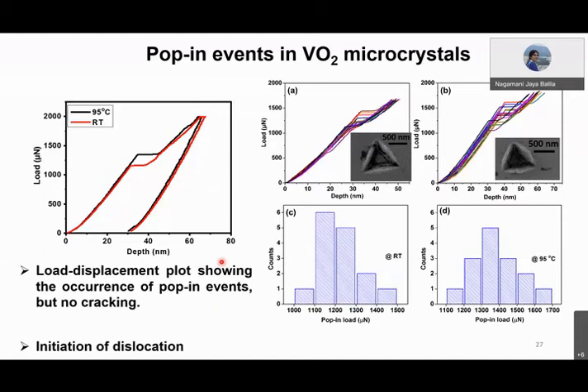Right. The reason we thought of putting this histogram, probably I should not go to the CRSS level, but it seems clear that the scattering, whatever we are seeing, is happening consistently within a small window. We always found it above 1 millinewton, between 1000 and 1500 micronewton. And within that, whenever we looked with AFM and SEM, we did not find evidence of cracking. So definitely we think it has something to do with the initiation of dislocation.